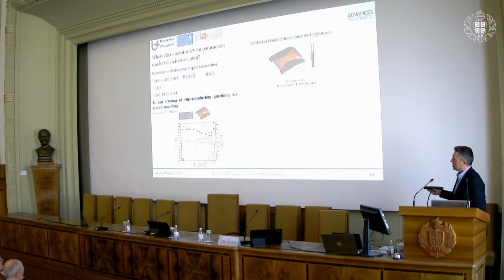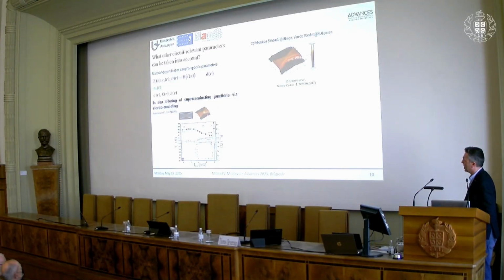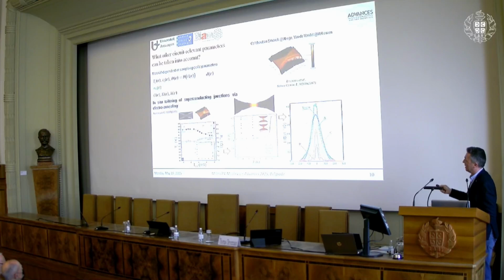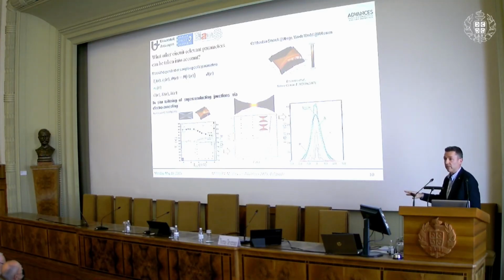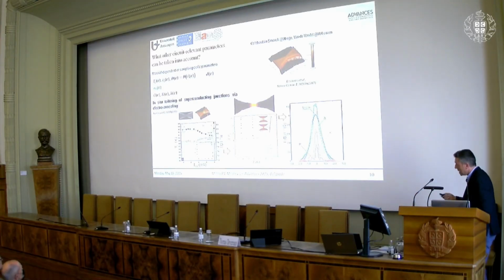We can also put spatially dependent parameters, be it inelastic scattering, mean free path, heat balance equation, the normal state conductivity, thickness, all of that can be done with 1 nanometer resolution. And this was proven in these previous papers. So we take from experiment directly the shape and all the properties that experiment can give us. For example, here was TC that was varying from one place to another, mean free path that was varying from one place to another, and we put that in the simulation without any fitting parameters. And it seems to work.